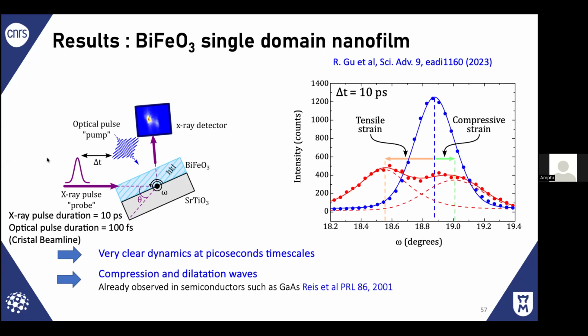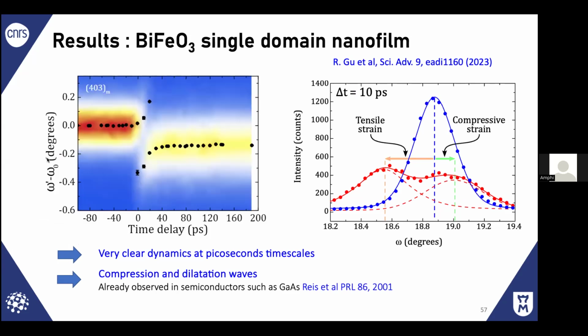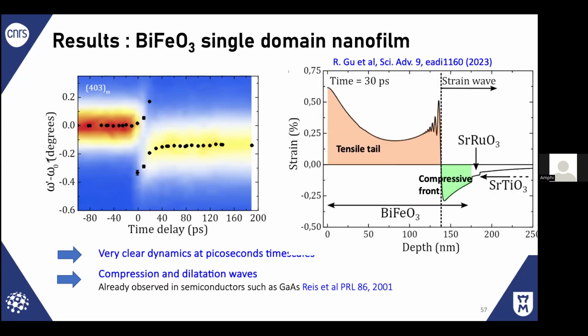There is a bipolar strain pulse. So there is one part which is tensile and one which is compressive. And this is when, if you look at how the Bragg peak changes as a function of time, you will get that variation as a function of time. And this is exactly consistent with the model that we discussed before.